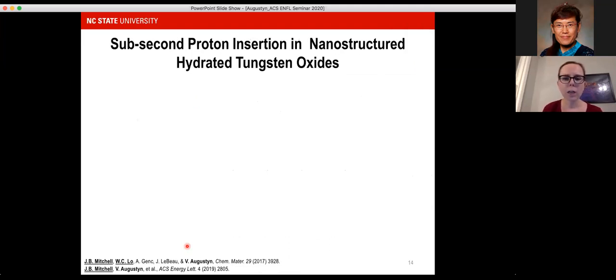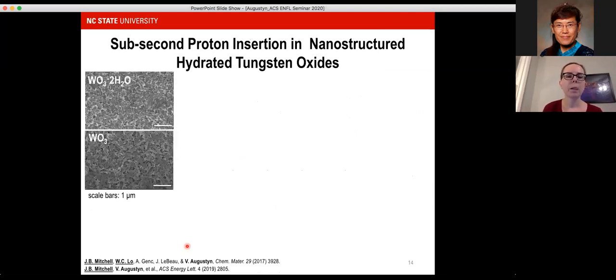We couldn't measure any diffusion coefficient of those water molecules. So now let's talk about the electrochemical behavior, because this is where things get really interesting, at least for us. We observed the same type of phenomena in the larger scale particles, but I want to show you in particular the results we obtained from electrodeposited thin films. So this is the hydrate thin film, this is the anhydrous thin film.